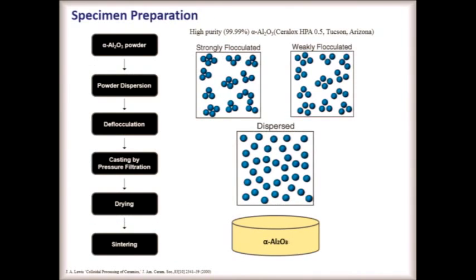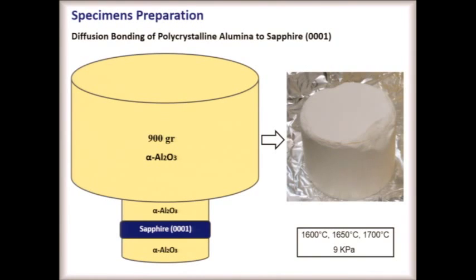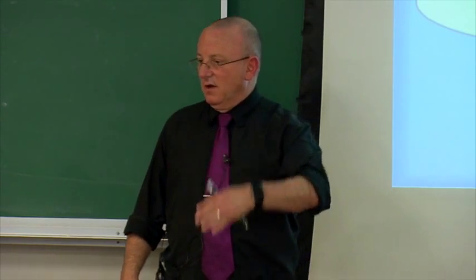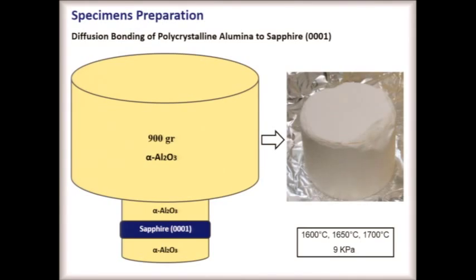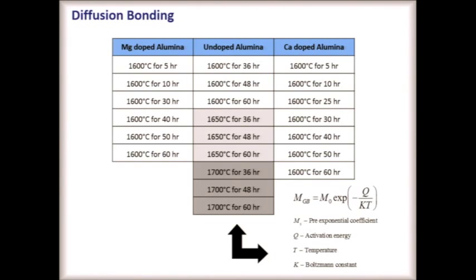And then we prepared these specimens where we either did not dope, and we'll call those undoped, and we doped with magnesium, and we doped with calcium. We're going to ignore silicon because it's extremely problematic. We used the same technique and pressure filtration to make laboratory controlled samples. We also did diffusion bonding experiments where, in a very simple way, we made a sandwich of sapphire with our polycrystalline alumina, and that way we could look at the growth rate of the basal plane into these doped or undoped materials.